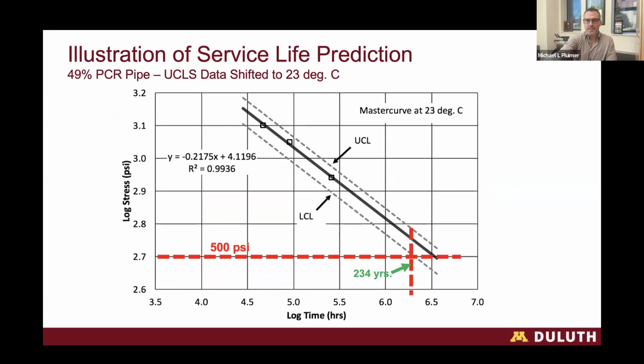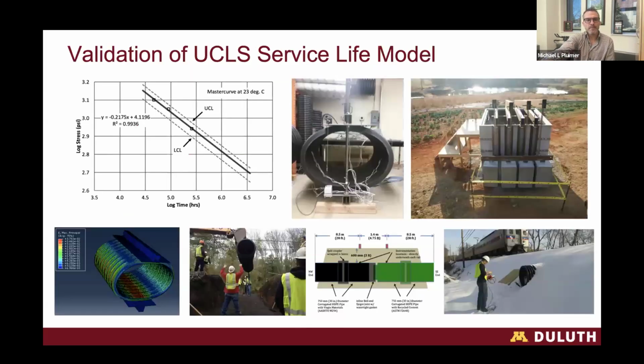500 psi is a very conservative assumption for the buried stress in a plastic drainage pipe. It assumes a fairly high deflected pipe and a condition that we typically don't see at stress levels at this level. But it's a number that's been used traditionally in the plastic pipe industry, especially in the case of Florida Department of Transportation in their 100-year service life model. So that's why we select 500 for our data point there.